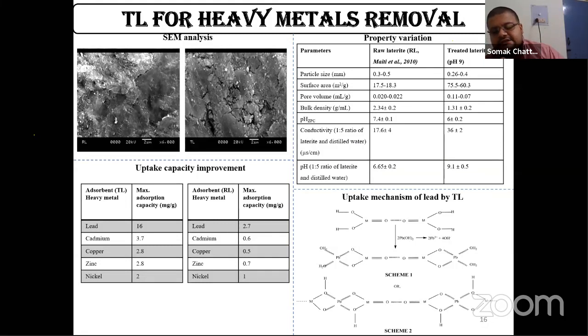This led to the conclusion of two schemes which can be theorized for the uptake mechanism of lead by treated laterite. This is the structure of the adsorbent containing oxyhydroxides, and when lead hydroxide is put in a solution, it usually ionizes into lead and hydroxyl ions. This lead gets exchanged with the oxyhydroxide bond, and it forms an intermediate structure, either as in scheme 1 or as in scheme 2.